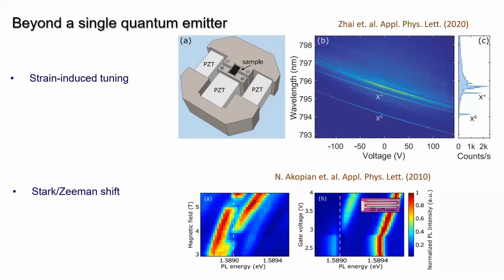So how do you achieve that? There are a number of different ways to change the frequency of a two-state system. There's Stark shifting. That's where you apply an electric field. You can do that by putting a nanopatterned metal very near to your emitter, and then putting a bias voltage there. The electric field gradient will actually stretch that molecule and make it emit at a different wavelength. You can use that to tune the wavelength to be what you want.